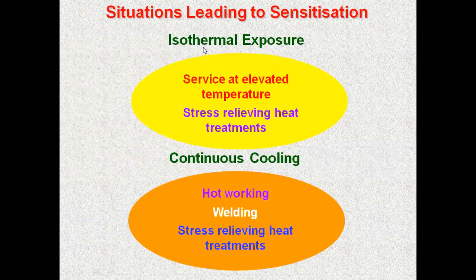This can happen either due to isothermal exposure, due to the service temperature or stress relieving heat treatment, or due to continuous cooling, either during hot working or welding operation or stress relieving heat treatment. And this heating and cooling between the 400 to 750 is unavoidable during this kind of isothermal exposure and continuous cooling. And how to avoid this sensitization?